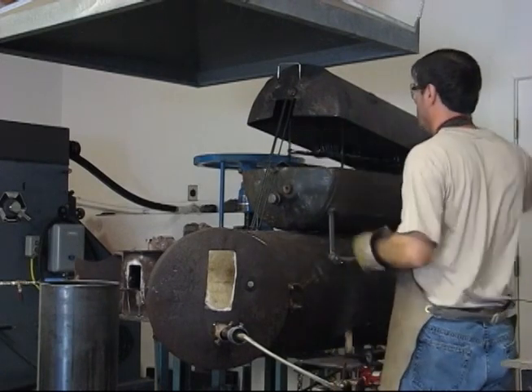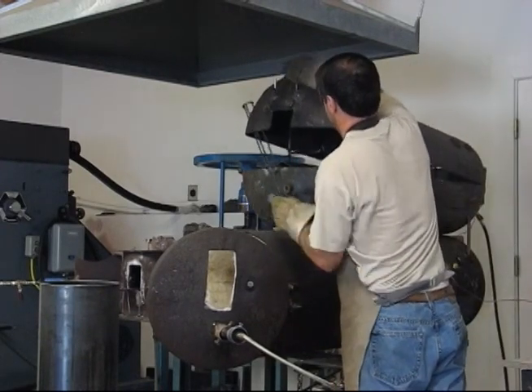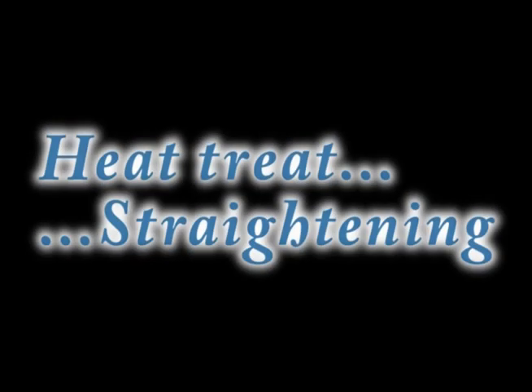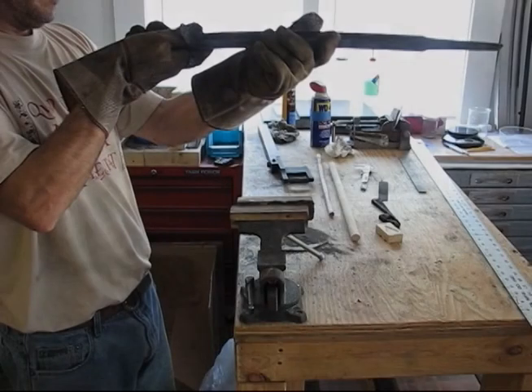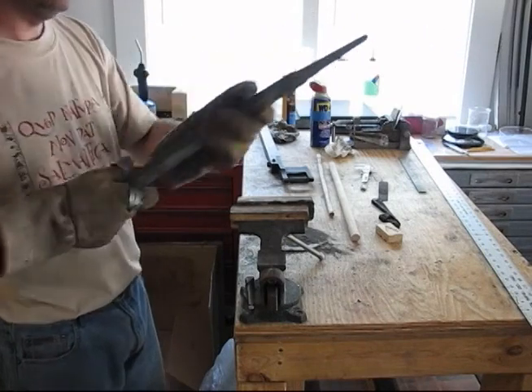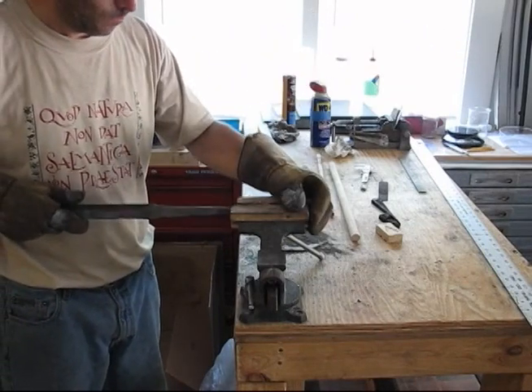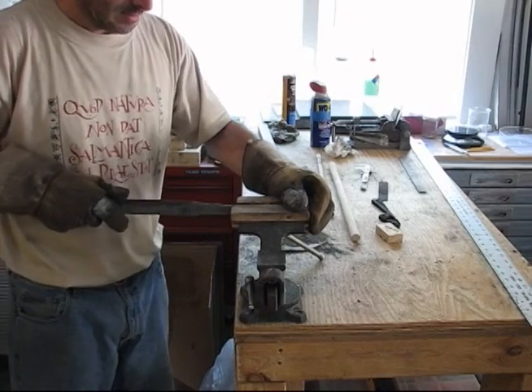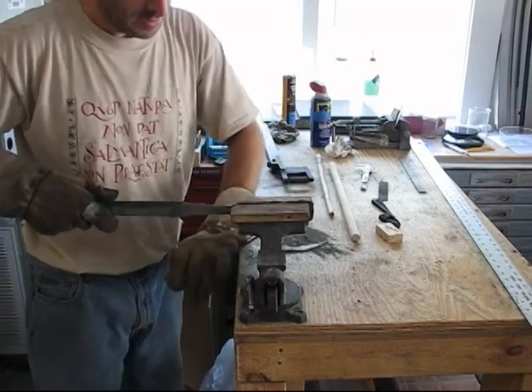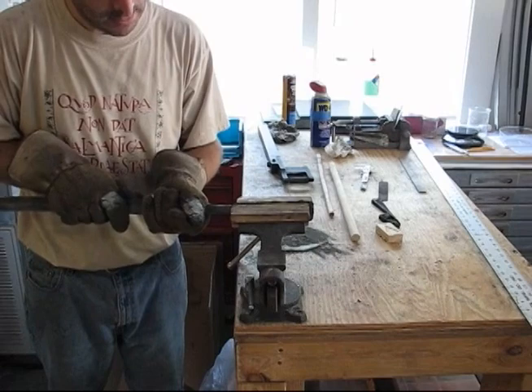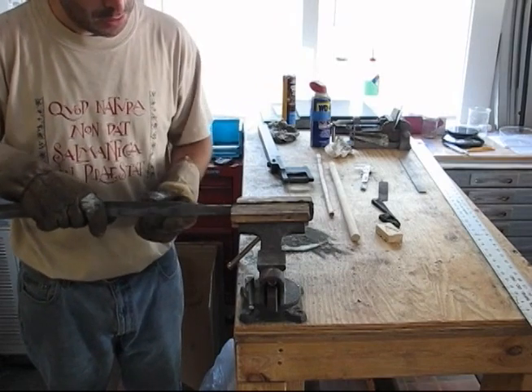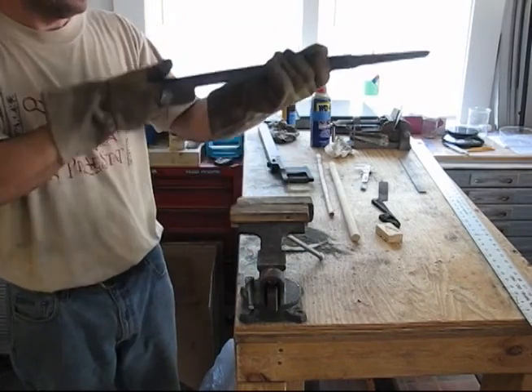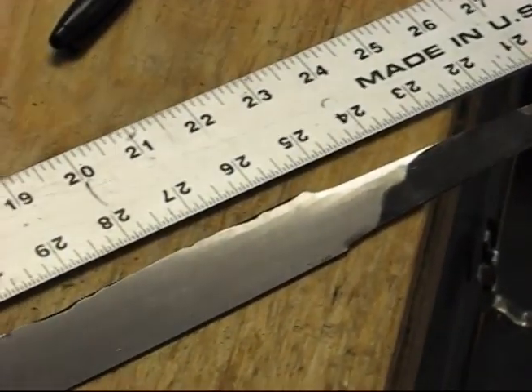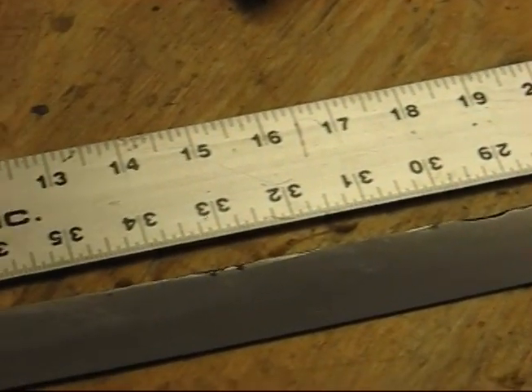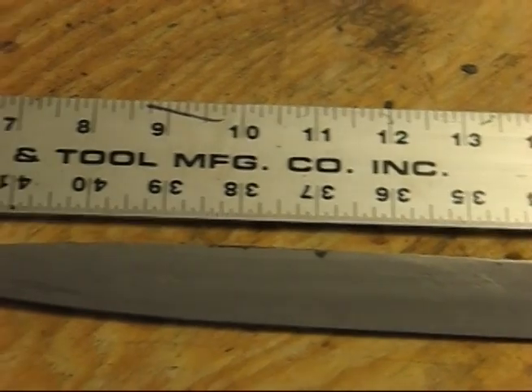Two cycles of tempering, lasting an hour each, will suffice for this blade. The best opportunity to safely straighten any warps in the blade caused by the hardening is after the tempering cycles, while the blade is sufficiently hot. Fortunately, this lucky blade did not need a whole lot of straightening.